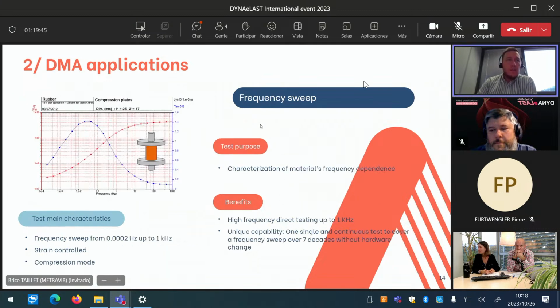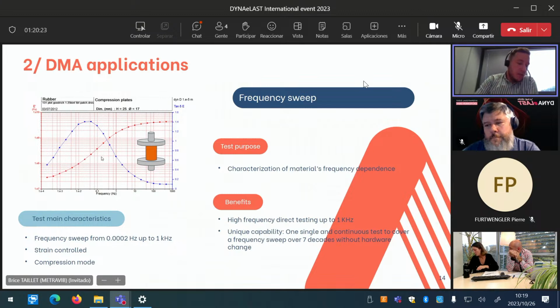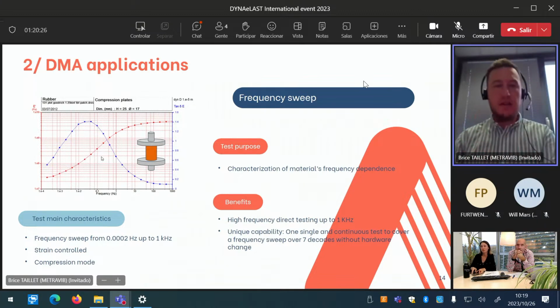Frequency sweep right now. Frequency sweep is quite a common test in DMA. Quite simple. We would like to characterize the materials' frequency dependence. Okay, so we are able to perform from very low frequency to a very high frequency. The aim of this illustration is to show a frequency sweep from 0.0002 Hertz up to 1 kilohertz in one single measure. Of course, in strain control, in compression mode. Okay, and the advantage of DMA from Metravib is you are able to perform this test in one single measure.